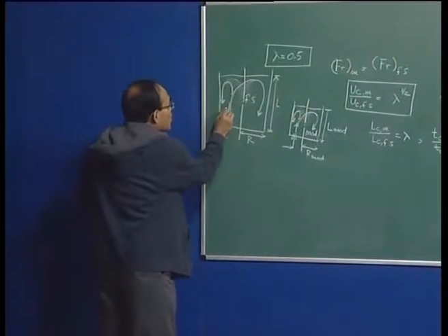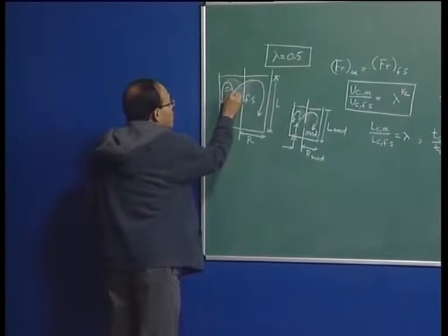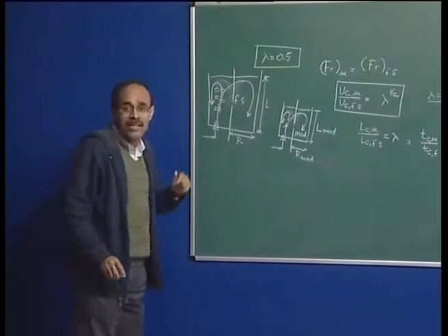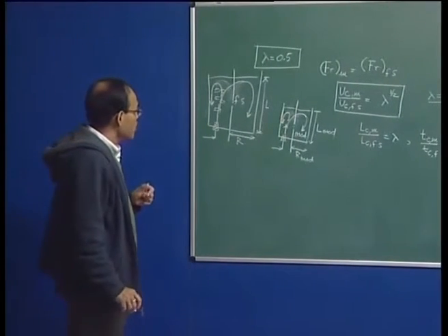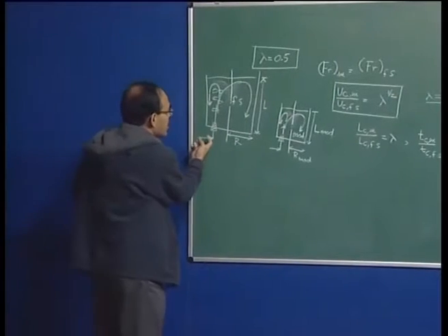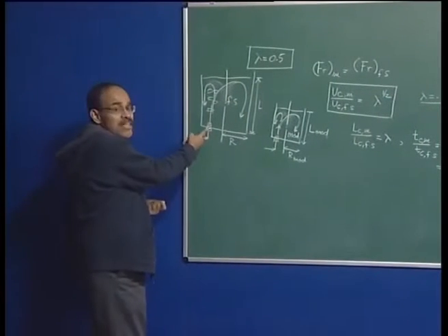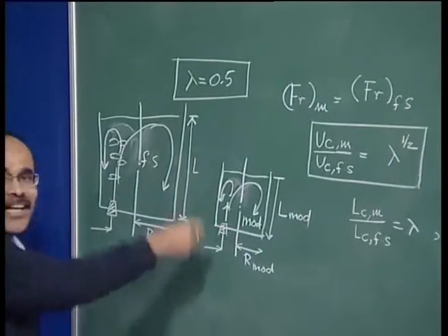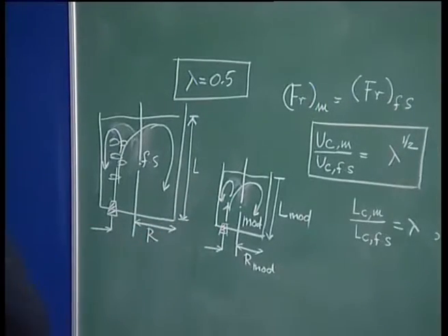It depends on the equilibrium size of the bubbles or the distribution of bubbles in the system itself, which is governed by thermophysical properties of the fluid. So, whether the injection of gas in the model and the full scale system is by porous plug, or I use a nozzle or an orifice here, it has hardly any consequence.